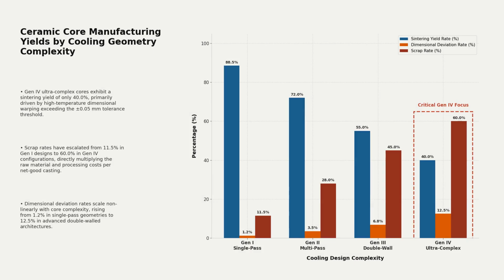Modern gas turbines operate at temperatures exceeding 1,600 degrees Celsius, surpassing the melting point of their nickel-based superalloy blades. To survive, these blades require intricate internal cooling passages formed during casting by high-precision ceramic cores. As cooling geometries advance to double-walled architectures, physical manufacturing yields collapse. Generation 4 ultra-complex cores exhibit a sintering yield of just 40%, driven by high-temperature dimensional warping.